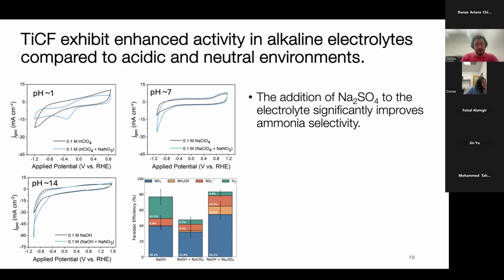which was actually a sort of a surprise to us, because I don't know if anyone has used titanium foil for nitrate reduction to ammonia. It only really works well in very acidic environments. So it is the same material, but in a different configuration. And we hypothesized that it's because titanium for doing this reaction needs a lot of availability of protons per active site. And because we're minimizing the amount of active sites of titanium here, we have different needs of proton availability and we can operate at very high pH compared to titanium foil.